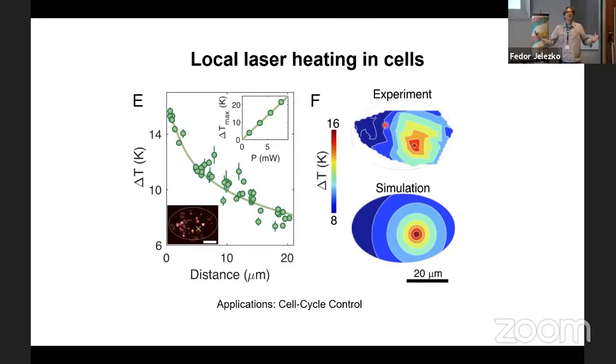And it's a very calibrated sensor because it's now a D of the spin. So it's not affected by any molecules outside, pH and so on. The effect you look at is the lattice constant of diamond. So it might be affected by pressure, but to compensate your temperature dependence with pressure noise, you need very high pressure. The diamond lattice is very, very, very incompressible. So this temperature effect on the spectral line of the NV center is a very self-calibrated measurement device.